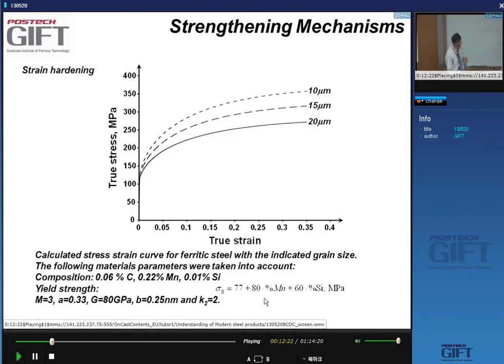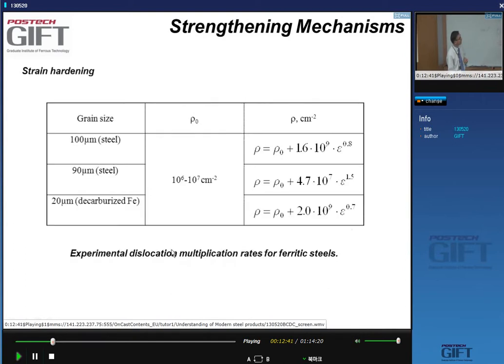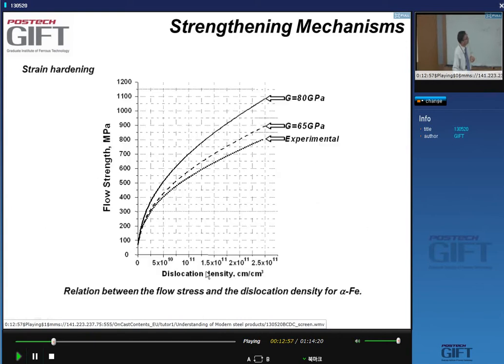Right, so if you want to know what the yield strength is, you take the lattice friction times the strengthening that was, for instance, taken into account here for manganese and silicon alloying. And these are some equations that have been published on the dislocation density variation with the strain. And these are experimental multiplication rates for dislocations. So it's the dislocation density that basically gives me the strengthening in the flow strength.